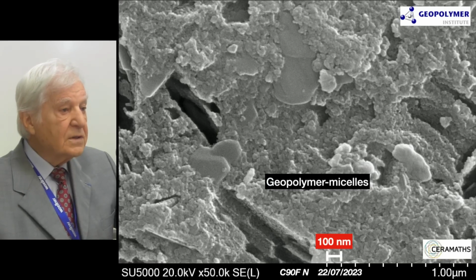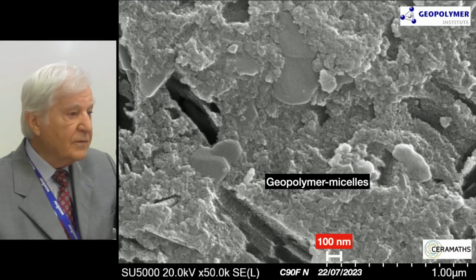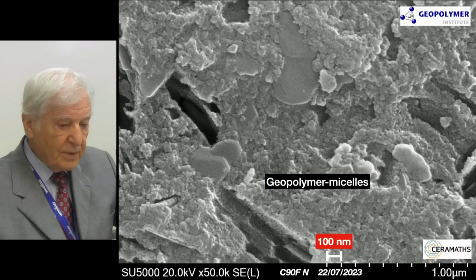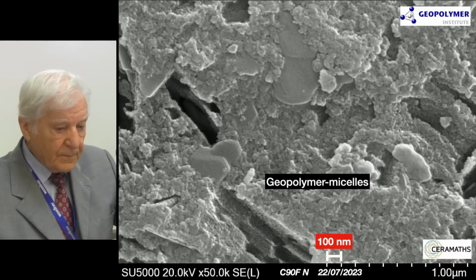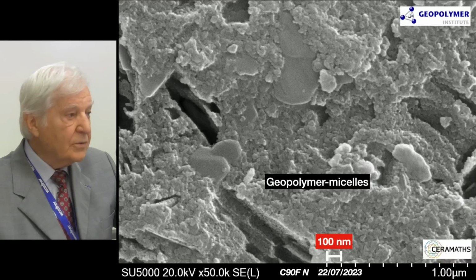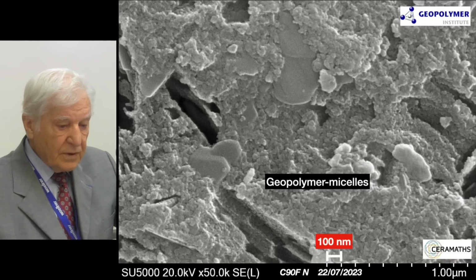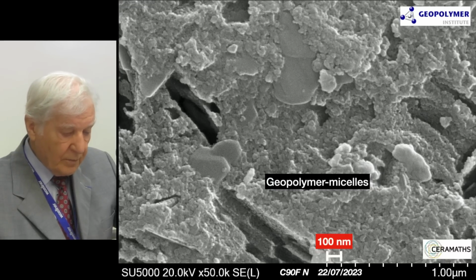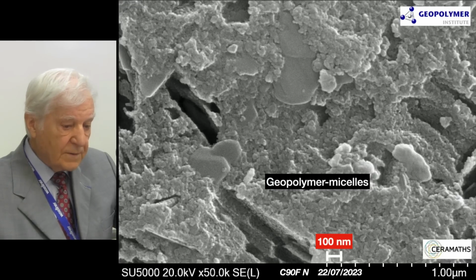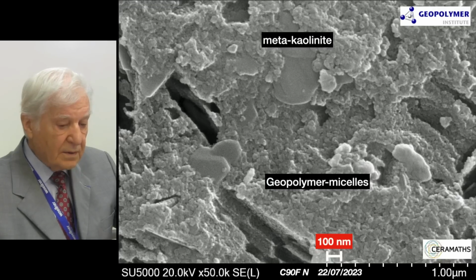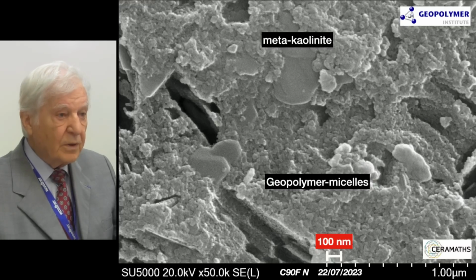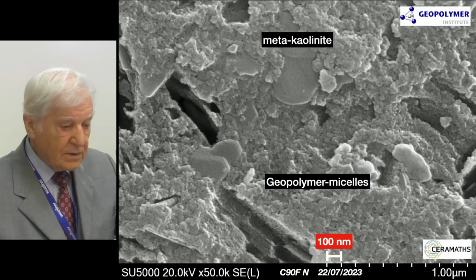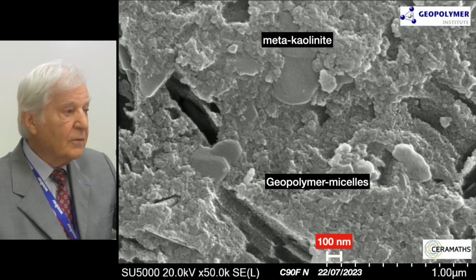We took one of these new commercial metakaolins as received from the supplier to make a potassium-based polysialate siloxo geopolymer item. Under the scanning electron microscope, with very high resolution, the subscale is 100 nanometers, the matrix of the potassium-based polysialate siloxo geopolymer is made of individual geopolymer micelles, identical to the previous ones, but we see also intact very thin hexagonal crystals of metakaolinite embedded in a geopolymer matrix with nano geopolymer micelles. In other words, the geopolymerization was not complete.